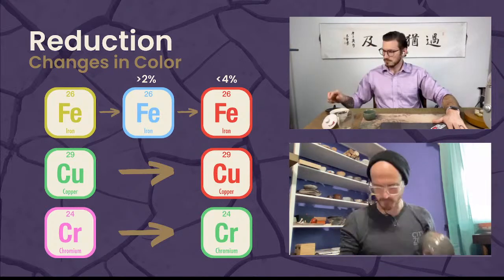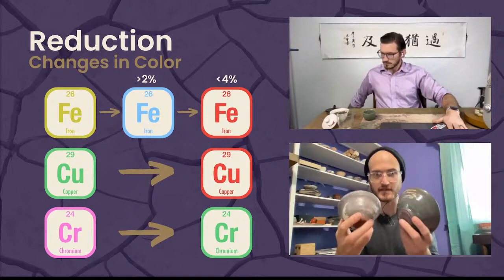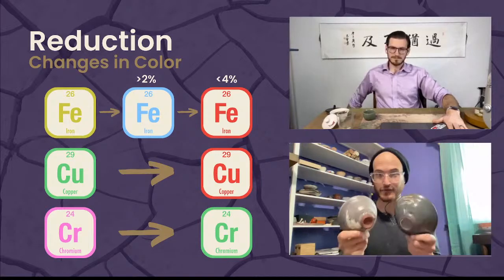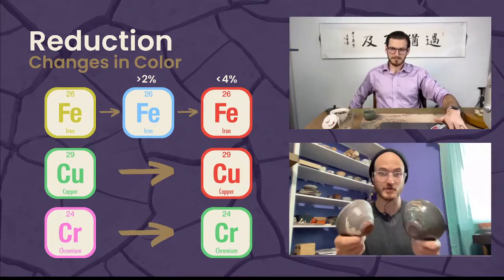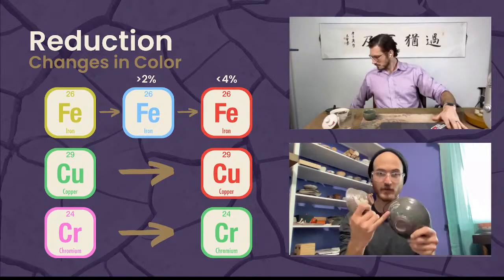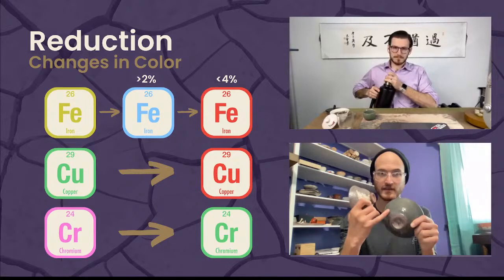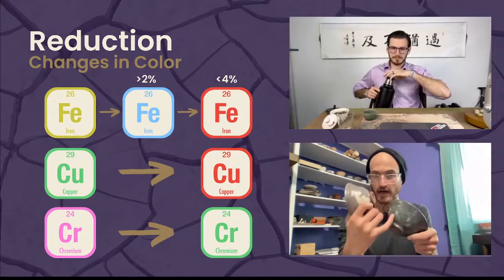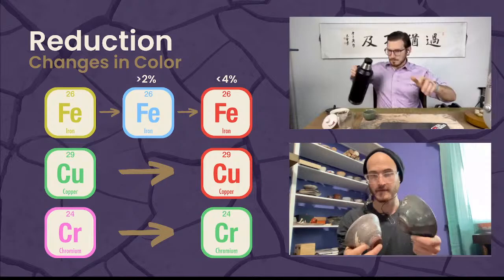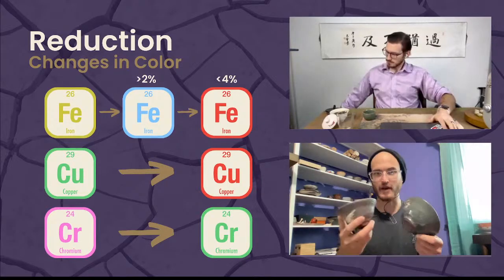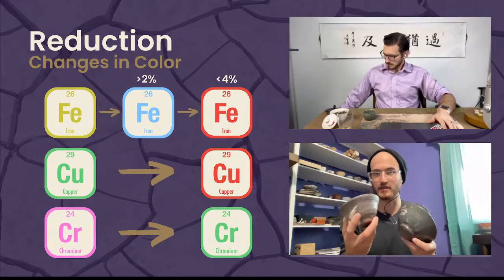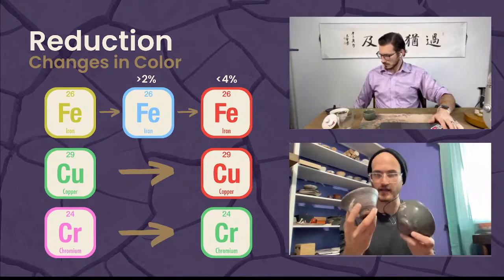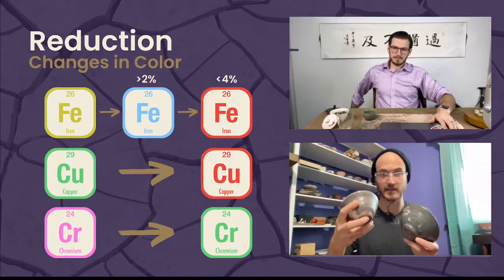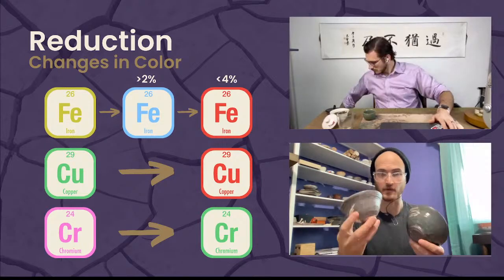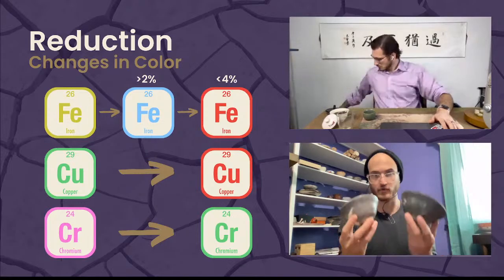So believe it or not, these are the same glaze and the same clay, the only difference being that one was exposed to reduction. The heavier melting power of iron in this glaze made it much smoother and shinier, and it turned it blue. Whereas this one, because it's a higher fired glaze, one that wants more heat, when I fired it in oxidation, the iron has no action on it. The clay itself is not melting and incorporating with the glaze, so you end up with this frosty white color. So really, a big difference.